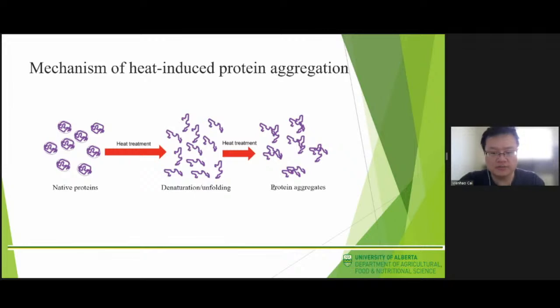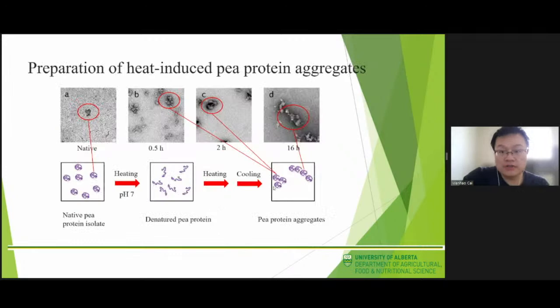Despite the potential, gels prepared from pea protein aggregates have been seldom investigated. So in my research, I will investigate the gelling property of such kind of protein aggregates. In my research, heat-induced pea protein aggregates were prepared by incubating the pea protein solutions at 90 degrees, neutral condition, for different times, like half an hour, 2 hours, and 16 hours, to observe the morphology of pea protein aggregates by TEM imaging.